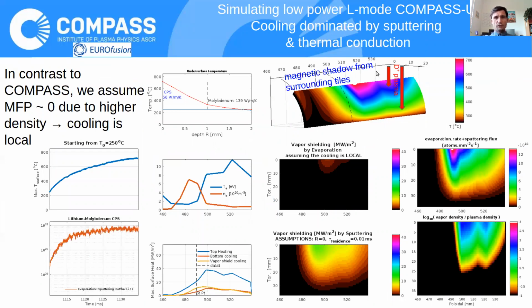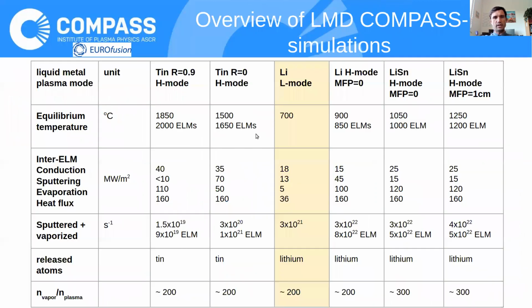So now we took those data and put them into this model. So again, plasma flow from this direction at high incidence angle. The surface will reach up to 700 degrees Celsius, and there will also be heat conduction into the bottom of the target, which we assume to be cooled probably by water. And you can see that the cooling will be about 15 megawatt per square meter, and otherwise the surface temperature will be dominated by sputtering and only very weakly by evaporation, because the surface temperature will be relatively low. So this is for L-mode, which you could see here summarized.